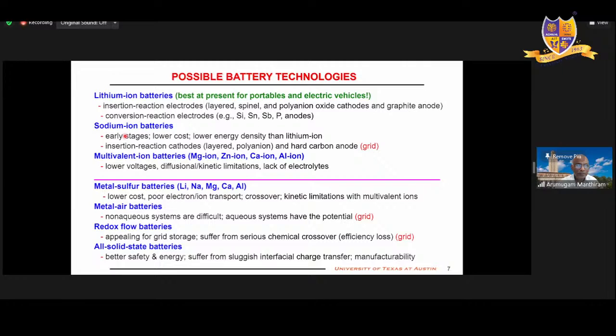2 or 3 problems. You see the redox energies here. Lithium is way up in the top. Sodium is here, a little bit less voltage. If you go to other zinc or aluminum, magnesium, they will have lower voltage when you use as an anode. So voltage will be decreasing first. Second,